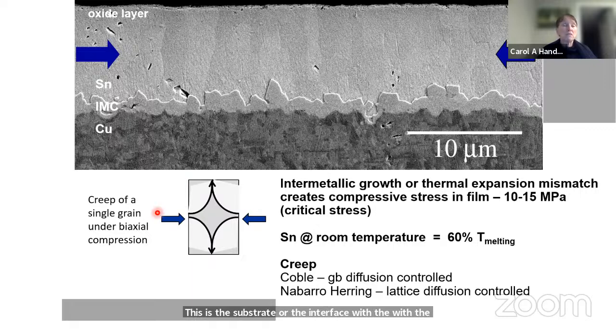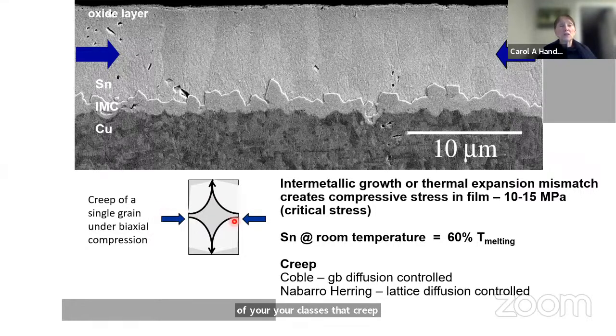So if you remember from some of your classes, that creep of a single grain under biaxial compression. So here's the stresses here. What happens is you end up with a stress gradient between the compressive grain boundaries and the free surfaces. So you get net motion of atoms from the boundary to the free surfaces. And so that's called, if it's grain boundary diffusion control, Coble creep. And if it's a lattice diffusion control, it's Nabarro-Herring creep. So that's a way that all of the grains in the whole structure could relax.